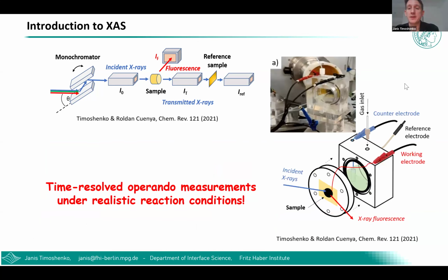This is the typical electrochemical cell we are using in this experiment. It's actually very simple. It's basically a cube filled with electrolyte, potassium bicarbonate in our case. The catalyst is deposited on a carbon electrode and taped with Kapton tape on top of this lid. We measure it illuminated by X-rays from the back through the carbon and this Kapton tape, and we collect the X-ray fluorescence signal from the catalyst under its operating conditions. So it's conceptually a very simple experiment, and it works very nicely for many different reaction conditions.